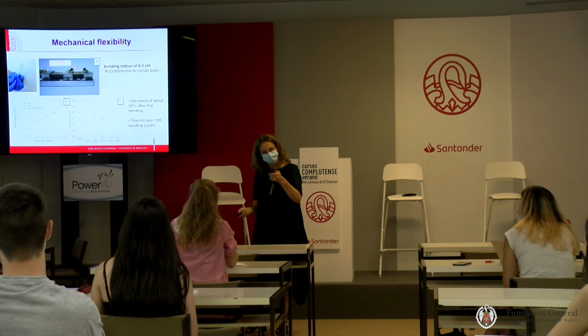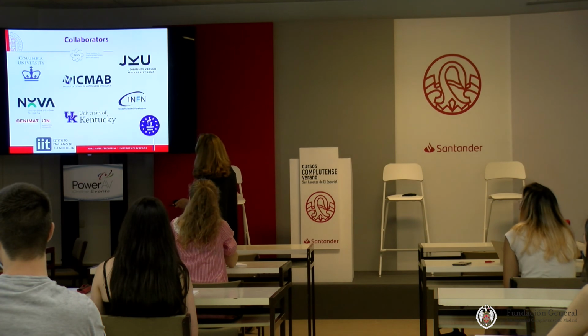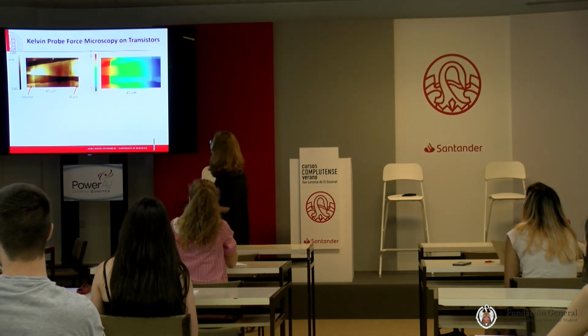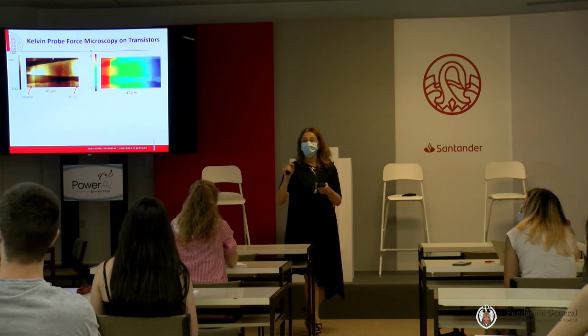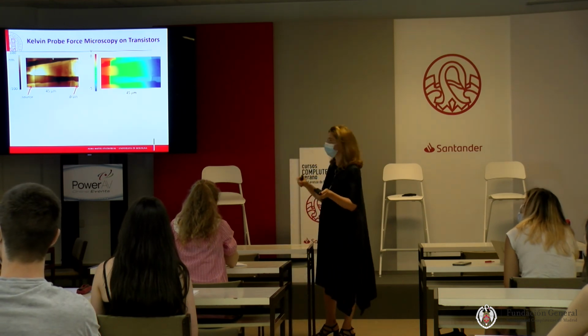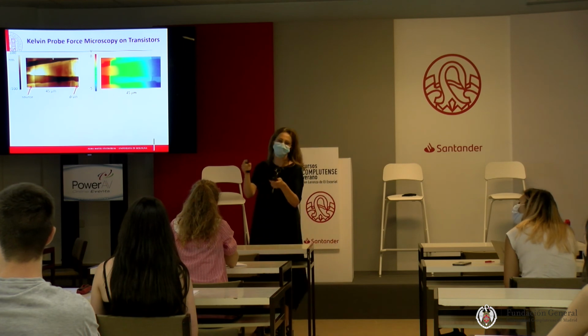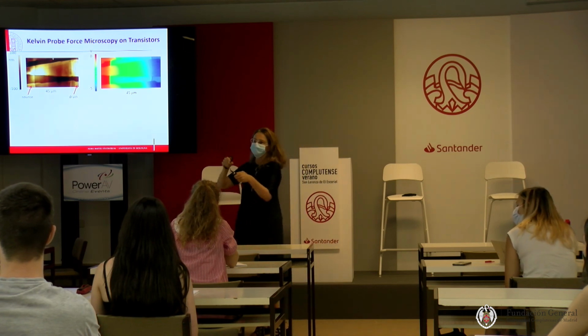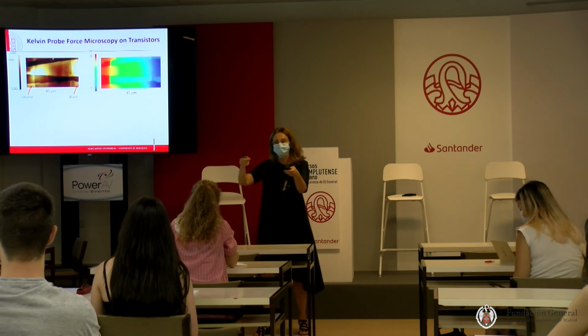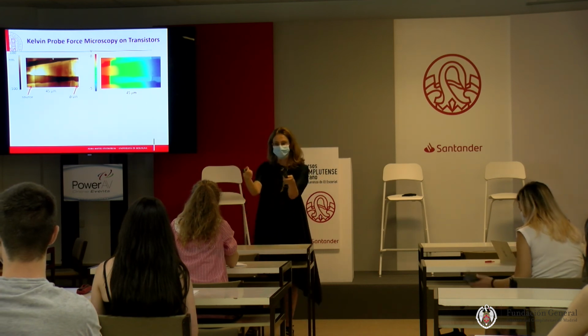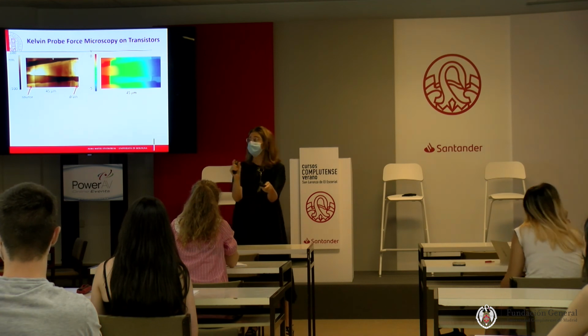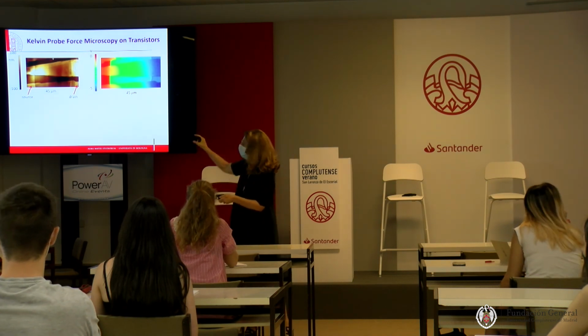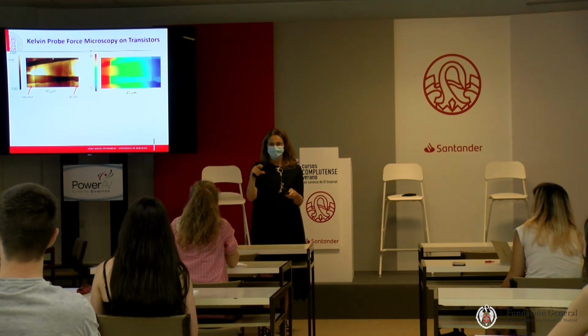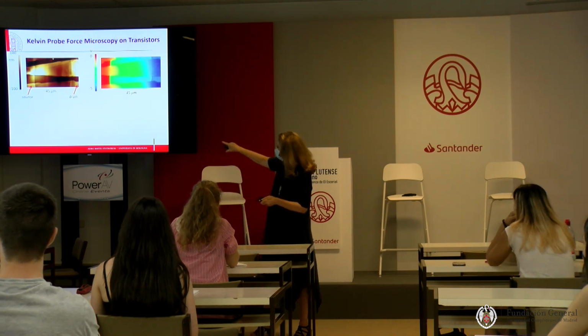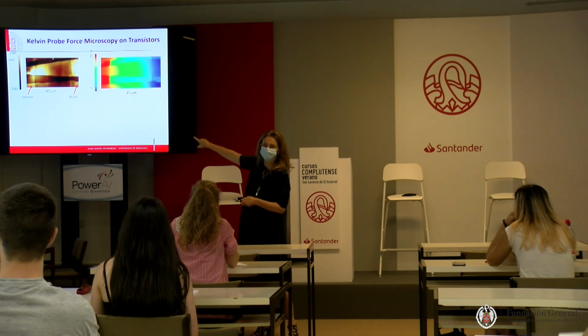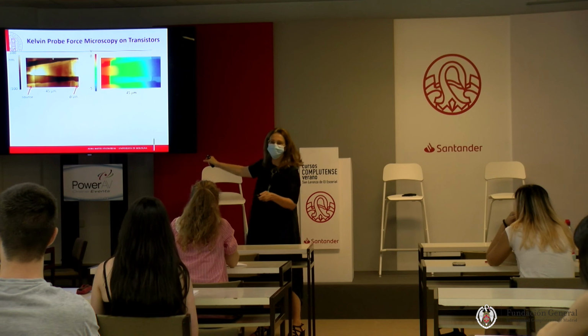So we asked why. Here it is. We did some tests under atomic force microscopy in the Kelvin probe force microscopy mode. We looked at one crystal that crossed between the source and the drain, and we bent it. The atomic force microscope is able to give you information at very, very small sizes. On the left-hand side there is the source, and on the right-hand side you can see the strip of the drain.